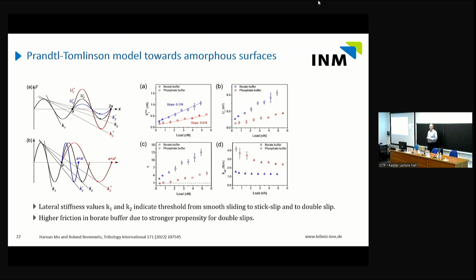Now what he wanted to do is, he said, let us do a Prandtl-Tomlinson model for amorphous surface. There's only one publication I know of with a model of stick slip on amorphous surfaces. So he tried to do the experimental physics approach, which means take a successful model and try to expand it towards what we need. So what he's done here is he has done this classical way of plotting force versus distance. So we have a sinusoidal force, which originates from some periodic potential, and we have these curves which correspond to a certain stiffness, local stiffness of the contact.